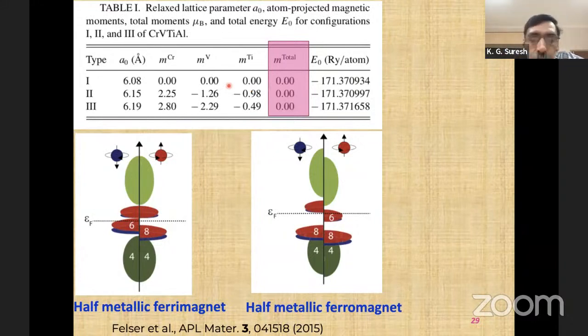In fact, this material was reported to be an antiferromagnet, with some mixture of metallic and insulating semiconducting properties and so on. But when we did this calculation and compared with our experimental results, we could show that it's actually spin gapless. The band structure has a spin gapless nature, and it is a ferrimagnet. It's a nearly compensated ferrimagnet. The magnetic moments and the directions are such that the net result is 0. Of course, it's true for all the 3 configurations, and they are not very far in energy. But in any configuration, the net magnetic moment is 0.